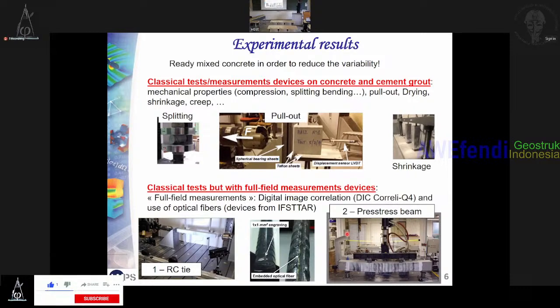So the experimental test. We used classical measurements, but also full field measurements. So what are classical measurements? We need to have access to drying shrinkage, creep. We need to have access to mechanical properties, Young modulus, tensile strength, etc. But also to the link between concrete and the rebar. So we also made some pull-out tests in order to identify the law between concrete and reinforcement.